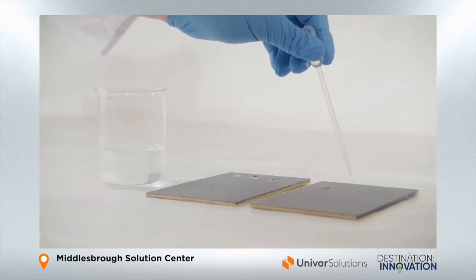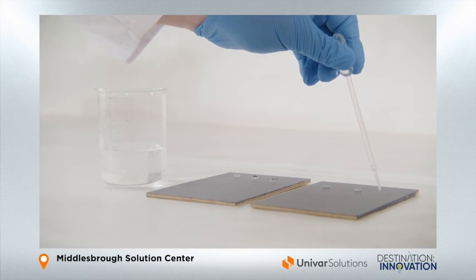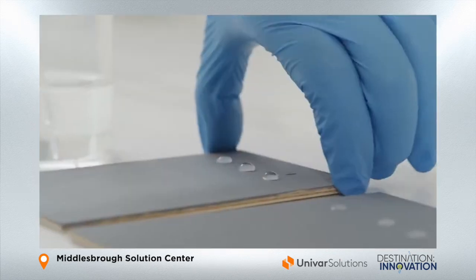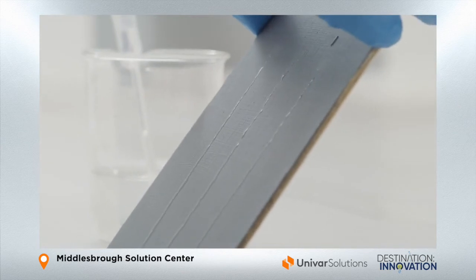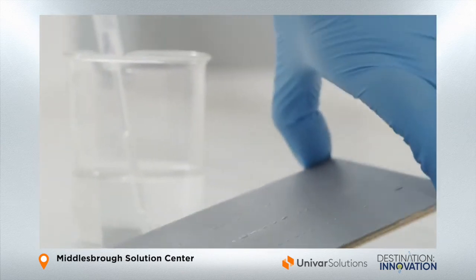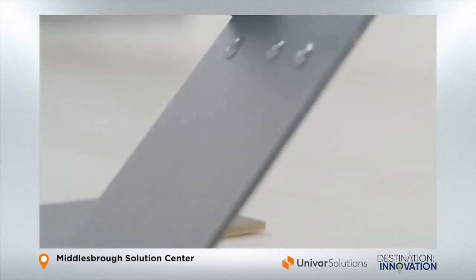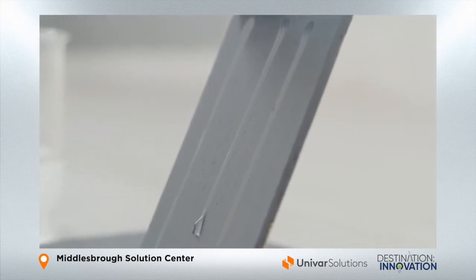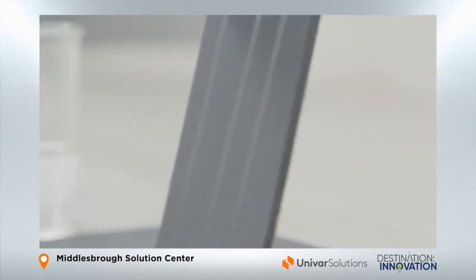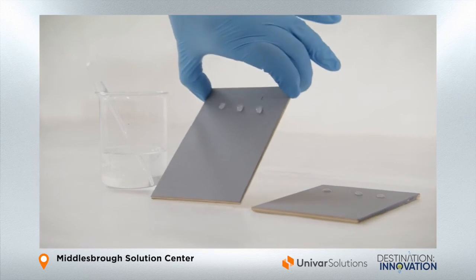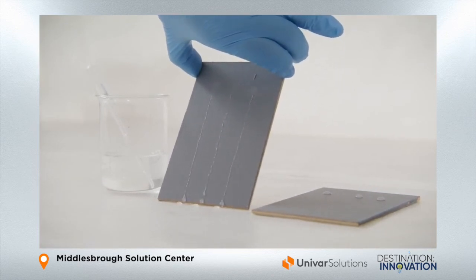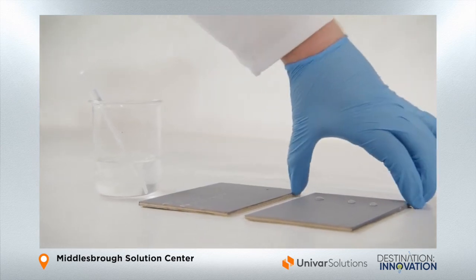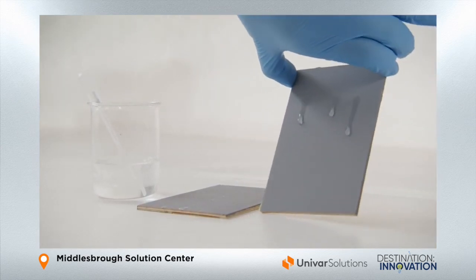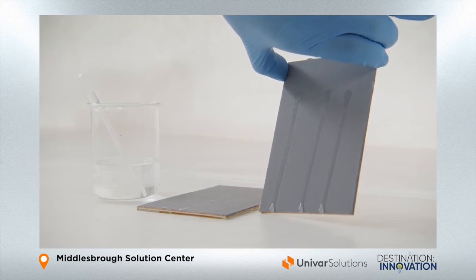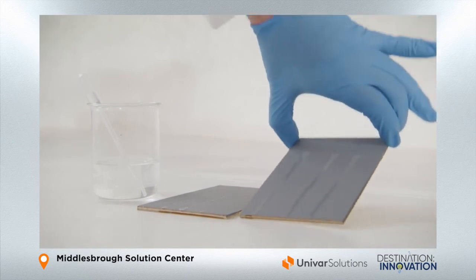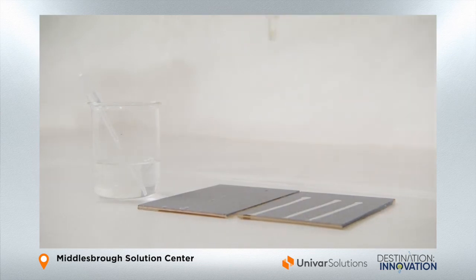The one on the right doesn't contain the additive, and you don't get quite the same water beading, but when you look at the test now, we're just allowing the water to drip down the panel as it would if it was raining, and you can see that the one without the additive, you're starting to get these snail trails appearing as the pigment is sort of being washed out of the coating. And that's maybe a bit easier to see from this angle. You can see the water beading effect there, the water repellency quite well with the silicone additive. And then without, it is just literally going down the coating. So if you've spent your day painting your fence outside, you don't want to then have loads of marks on the surface.